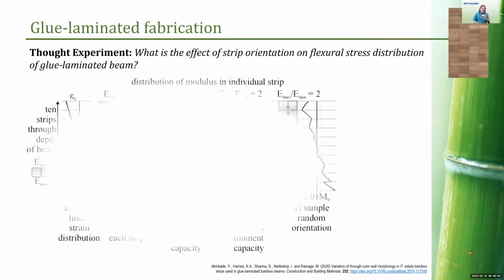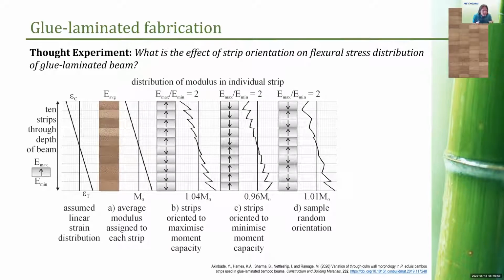And this is important. I'm going to throw up a thought experiment here for just a second. So imagine I'm just going to take a board, it's only got 10 elements in it. If I take the average modulus and the average behavior of this, I'm going to come up with a moment capacity for this board, a bending capacity. And what I can do then is think about, well, how can I orient those strips to maximize the moment capacity and to minimize it? And if I do so, I can vary my capacity by about plus or minus 4%. And we showed one random case here where this particular random orientation comes up slightly higher than the average. Other ones would come up lower.